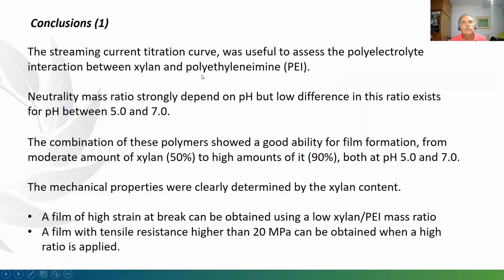Conclusions. The streaming current titration was useful to assess the polyelectrolyte interaction between xylan and polyethylenimine. Neutrality mass ratio strongly depends on pH, but low difference in ratio exists for pH between 5 and 7. The combination of these polymers shows a good ability for film formation from moderate amount of xylan to 90% of xylan for both pH. The mechanical properties were clearly determined by xylan content. A film of high strain at break can be obtained using low xylan-PEI mass ratio, and a film with tensile stress resistance higher than 20 megapascals can be obtained when high ratio is applied.